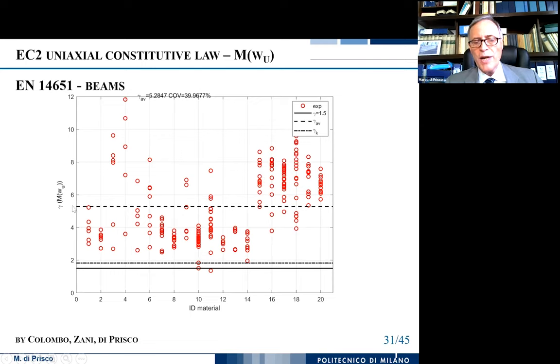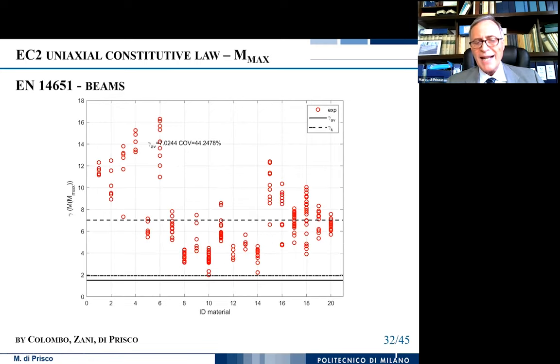You see that always you have an average safety factor which is very huge. And if you look at the characteristic value, of course, you progressively go towards a reduction of the safety coefficient. The same happens for the maximum bending moment. And this is very important to know. That means that for our material, looking at the maximum bending moment, not the bending moment for the ultimate crack opening, you are always guaranteed a very huge safety coefficient in the average.